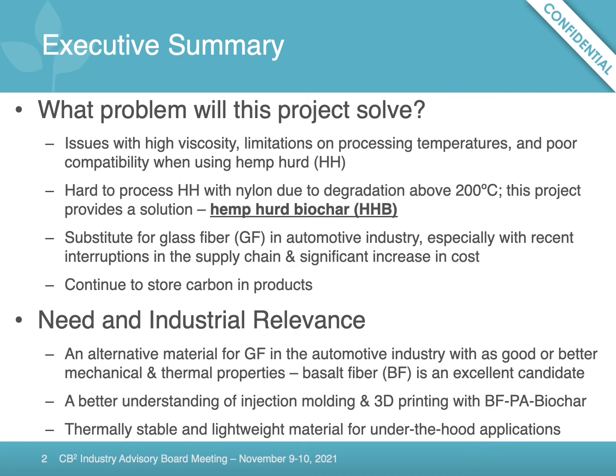The problems that this project will solve are as follows. We know that when biomass is used with polymeric materials during processing, whether it's injection molded or extruded, it generates very high viscosities. Also, the processing temperatures could be limited to below 200 degrees centigrade because the biomass will start degrading. Additionally, there could be poor compatibility between the biomass and the polymer.